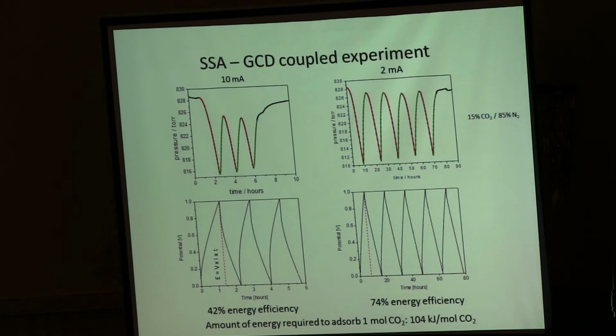So, furthermore, we were interested in the question, what is actually the energy efficiency of an adsorption-desorption cycle? To figure this out, we have coupled a supercapacitive swing adsorption experiment with a so-called galvanostatic charge discharge experiment. In a galvanostatic charge discharge experiment, you charge the capacitor at a constant current up to the desired voltage, which is in our case 1 volt. Then the area underneath the charging curve multiplied with the current gives you the energy that you have used to charge the capacitor.